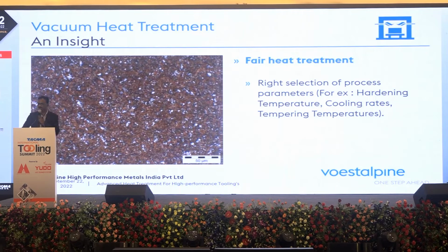If the tool steel manufacturer specifies a hardening temperature range from 1000 degrees centigrade to 1100 degrees centigrade, for example, you are supposed to do it at 1000, and you can also do it at 1100. So if you see the microstructure, it gives a clear picture: the total mechanical properties or physical characteristics, whatever they be, will be up to the level and at optimum conditions. This is termed a fair heat treatment that everyone knows.